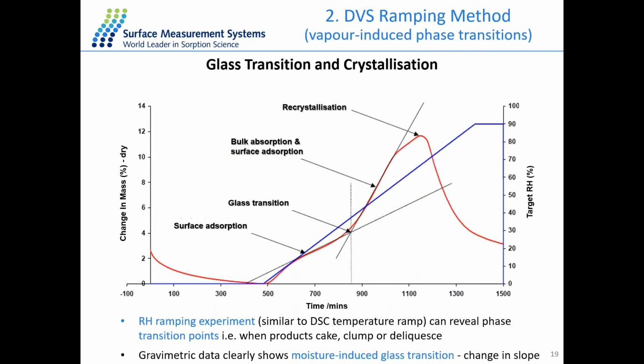And all the previous study is about the step method. The other method we normally perform with DVS technique is the ramping method, which is a quicker and easier way to measure the stability of the solid material. And it's very similar to the DSC temperature ramp. So in case of the DVS, we ramp the humidity from 0 to 90% RH at a constant rate.